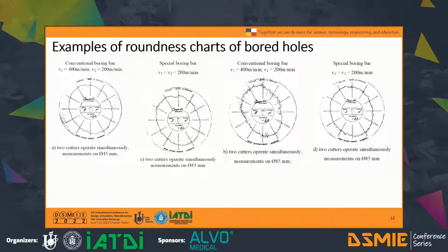It can be seen that the value of deviations from circularity during the operation of the second cutter doesn't differ significantly. However, in the case of the operation of the first cutter mounted on a conventional boring bar, after 10 boring operations these deviations increase significantly due to wear of the cutting blades. In this case, deviations from circularity when boring with a special boring bar change slightly.